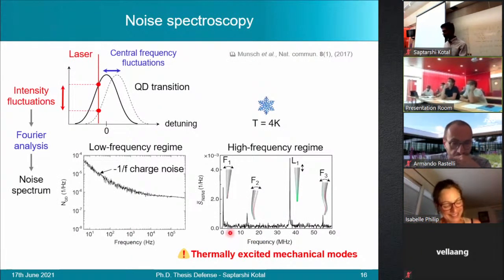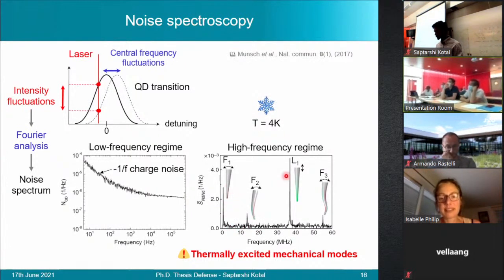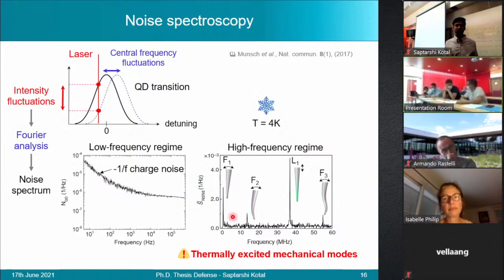So what we can do, by performing such noise spectroscopy, is get the relative intensities of the different modes of frequency. By comparing the relative frequency of, say, the longitudinal mode, which generates a stress which is uniform and acts like a reference, with that of the flexural modes, we can estimate the amount of stress that the quantum dot is undergoing. Then we can reversely find out where the quantum dot must be positioned across the radius, not the axis, to experience such a stress. And this was actually done by them, and it's mentioned in their publication as well.